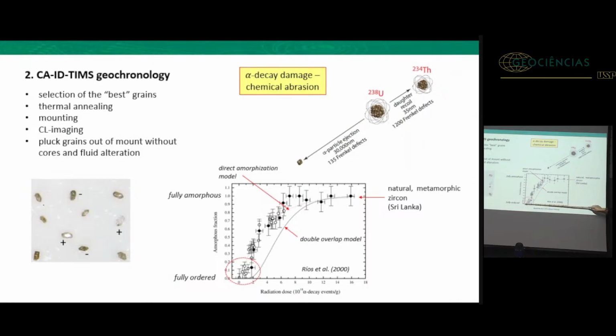So every one of these decays will create a damage, and when you quantify this in a diagram, this is 100% fully ordered zircon, so 0 damage. This is 100% fully amorphous, so 100% damage. Your zircons will align along a curve, and you can overlay such data with models, so direct amorphization model, double overlap model. These are models coming from the material sciences, and you see that when you are below a certain threshold, you like to have such zircons for analysis. So the least damaged zircon you would try to find for your analysis.